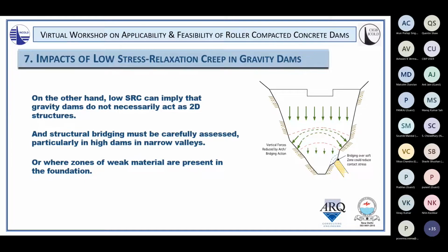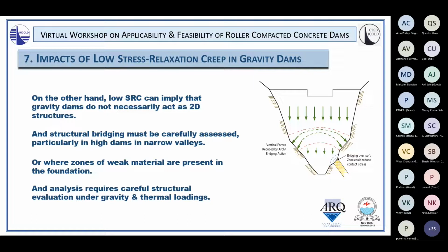That contact pressure can be less than the hydraulic pressure, and if we have an erodible material on a contact, this can obviously result in a very serious erosion beneath the dam. Consequently, analysis requires very careful structural evaluation of the dam structure under gravity and thermal loading. So our thermomechanical analysis must very carefully consider the process of construction and subsequent loading.